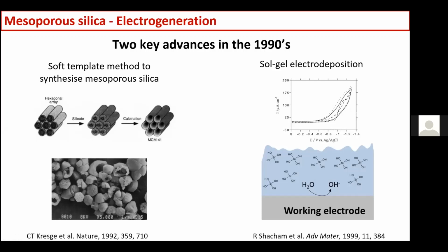And then a second study that was important for this work was the electrodeposition of sol-gel. There was work done by the group of Daniel Mandler in Israel, and he showed that if we apply a reductive potential at an electrode surface, in the presence of hydrolyzed silanes, then you would electrodeposit silica, and the amount of charge passing through the electrode determined the thickness of the film. So taking these two studies together,